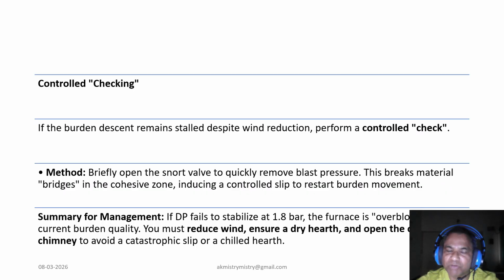So if your furnace is at 1.8 dp and it is not stable, you bring it down to 1.6 through 1.7 experimentation, and even if at 1.6 you find it is unstable, you need to reduce further. You must choose that delta p which remains stable in the furnace, and that is the only key. But if we just reduce the delta p, then our normal regime and speculating improvement will take time. So choosing the right delta p, which is signified by its stability, is the topmost strategy which is going to give us a result.